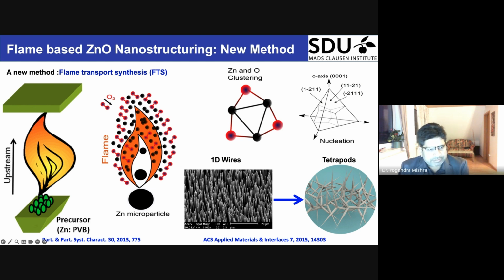If we put a substrate on the top, then one can grow 1D layers in different manners. There is a big field, I don't want to go into that. But if you are not putting any substrate on the top, then we have zinc and oxygen clustering, it's natural clustering, after nuclei are formed, and then we have growth along the four faces leading to formation of zinc oxide micro and nanostructure tetrapods.